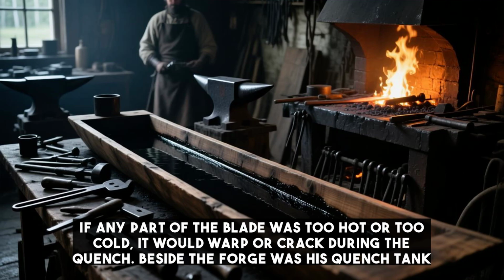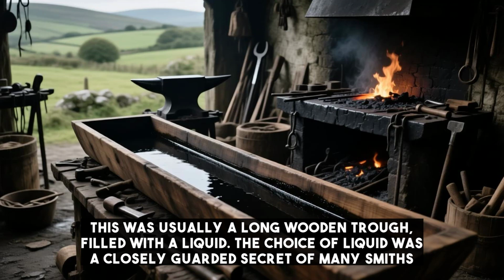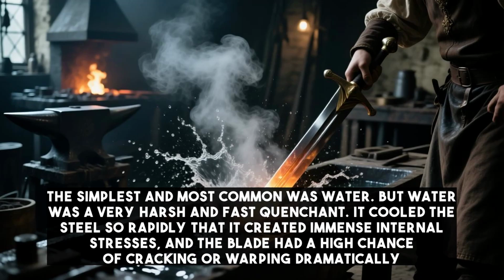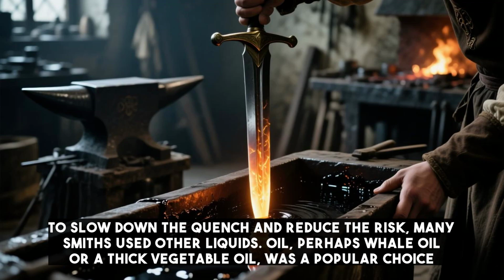Beside the forge was his quench tank. This was usually a long wooden trough filled with a liquid. The choice of liquid was a closely guarded secret of many smiths. The simplest and most common was water, but water was a very harsh and fast quenchant. It cooled the steel so rapidly that it created immense internal stresses, and the blade had a high chance of cracking or warping dramatically. To slow down the quench and reduce the risk, many smiths used other liquids.